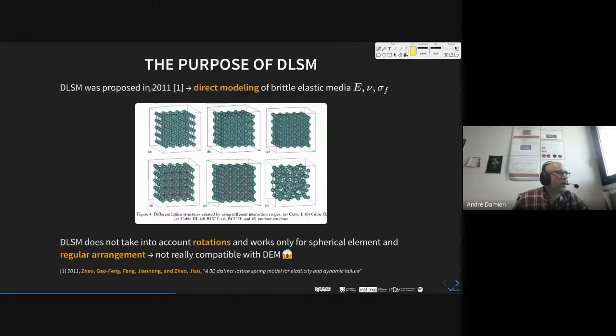This model was proposed around this date, and the idea is to have a direct model of brittle elastic media, which are defined only by three parameters: the Young's modulus, the Poisson's ratio, and a failure stress. This model does not take into account the rotations and works only for spherical elements and regular arrangement, as you can see here. This kind of geometry is not really compatible with our discrete element method. Now I will show some adaptation of this method to the standard discrete element method.